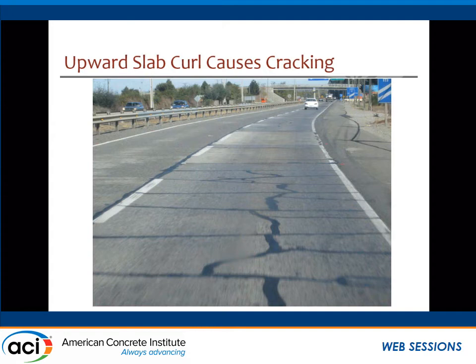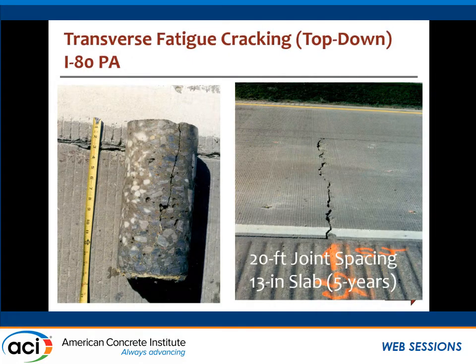So what does upward curling do? That can be pretty detrimental for a pavement. This is, of course, not the intermodal facility, but if you had excessive upward curling or excessive shrinkage gradients in the slab, it will result in top-down cracks. Here are some pictures of some extensive failures on highway pavements. Now that's a picture that Mike used to have from the study he did on I-80 Pennsylvania. You have a core at the location of a transverse crack. You see that the crack was initiated at the top of the pavement. These were 20-foot joint spacings, 13-inch slabs, which started failing 5 years after construction because the trafficking obviously exacerbates the stress development and increases damage to cause failures.